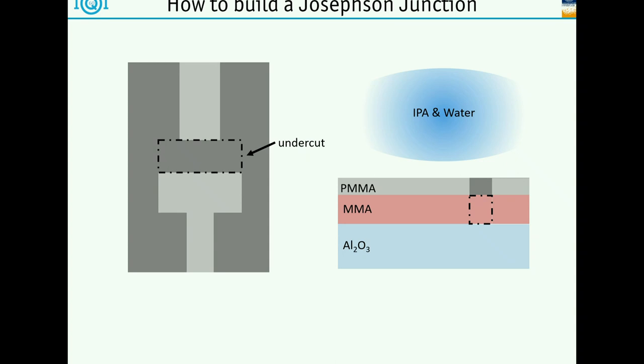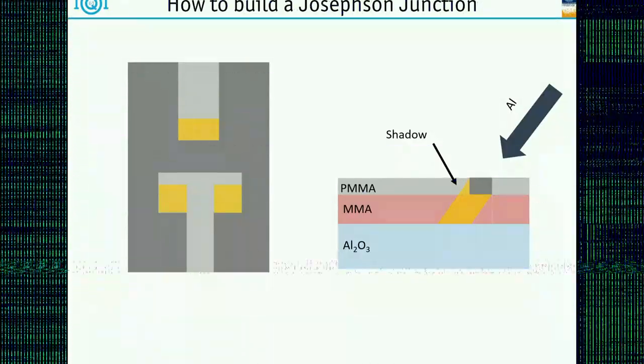So this is really everything here that's now open, and this is the bridge, so this would be a cut right through here through the center. So what we can then do is evaporate aluminum under an angle, and what will happen is that the bridge standing here and these edges will throw a shadow. So what will be deposited on the chip will be a thin film here right in that gap. Then we get the shadow from this bridge, which forms an opening there, and then we get another thin film here on the back. And there's also the shadow coming from this backside here.